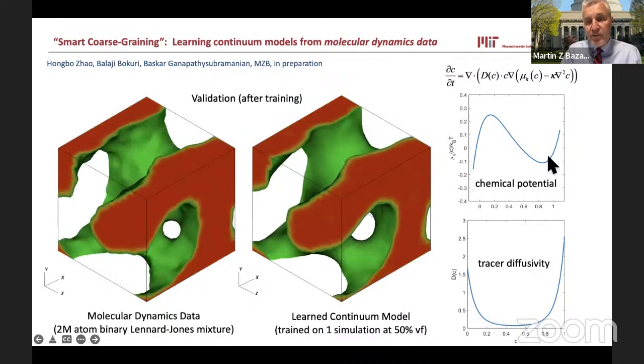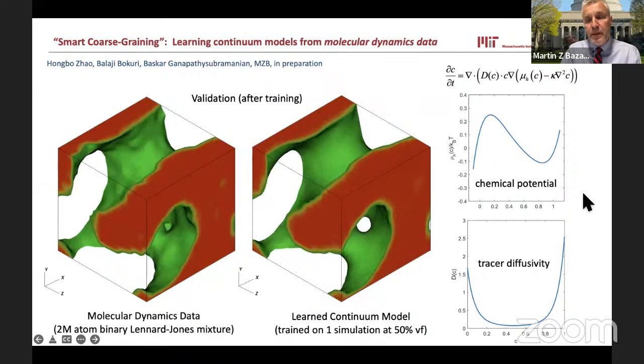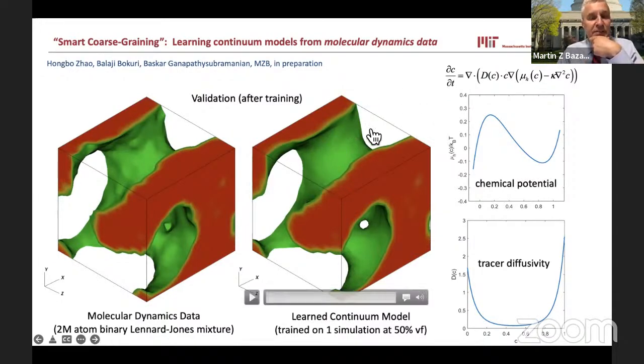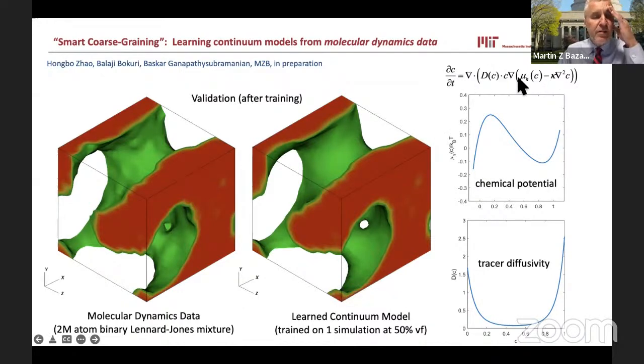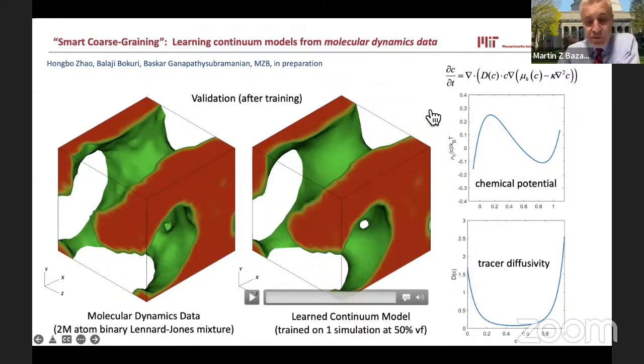And in fact, the chemical potential, which is the top plot, and the diffusivity are shown here. And so if you just simply know the right framework for the model, then you can learn these unknown functions, and we're essentially learning the physics. So rather than traditional science, which would postulate a model, and then you do some experiment, and you throw out almost all of your data and reduce it down to one number, like a diffusivity, here, by observing a system driven out of equilibrium and following the dynamics and generating a huge data set of images, we can actually learn the constitutive laws with tremendous accuracy. I was pretty amazed that even at the scale of only tens of atoms, this continuum model actually works so well. I mean, this is a very classical model for phase separation. I didn't even expect it would work this well for an actual molecular simulation. So I think that's an interesting result by itself.